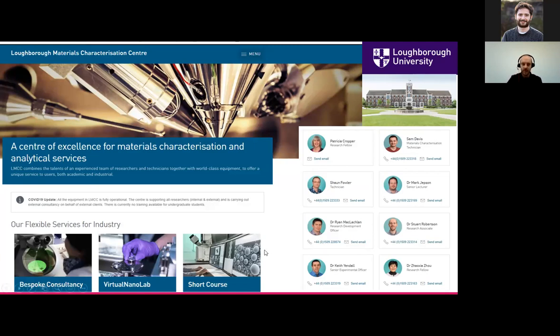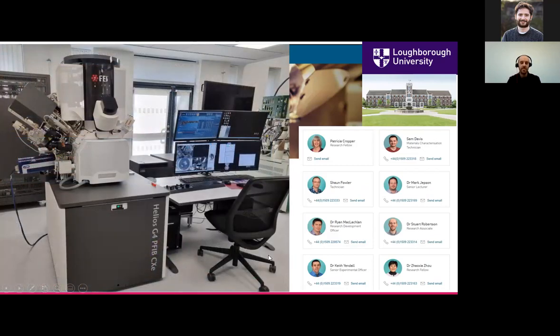We've got a little team of us, and I'm fortunate enough to look after our Helios G4 PFIB, which is around 3 or 4 years old now. It's a xenon plasma FIB system equipped with a multi-chem gas injection system, which has platinum, tungsten and carbon, and we have a Symmetry EBSD detector and a large area EDS detector, all Oxford Instruments. So it's a really nice system. We're very lucky to have it.